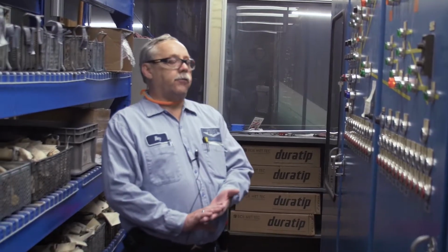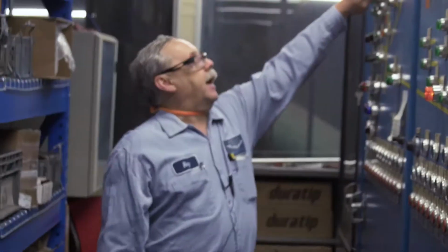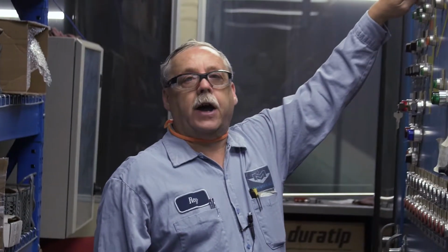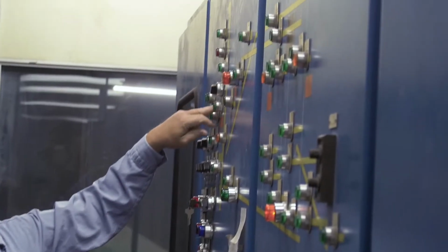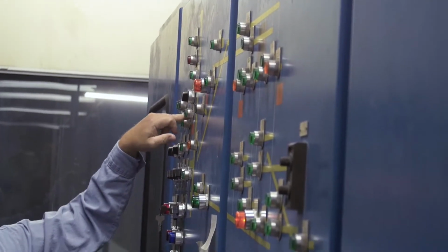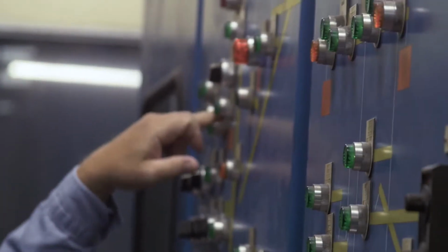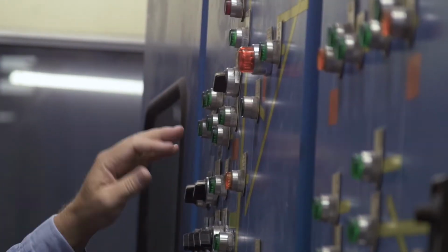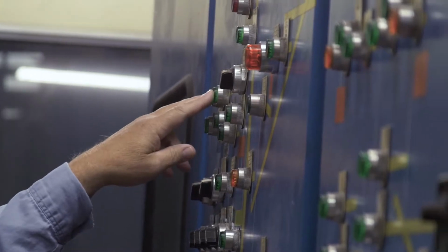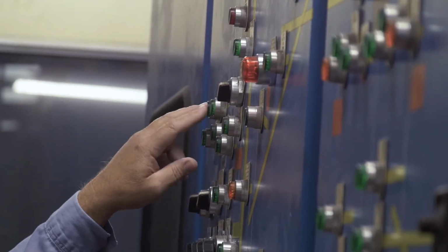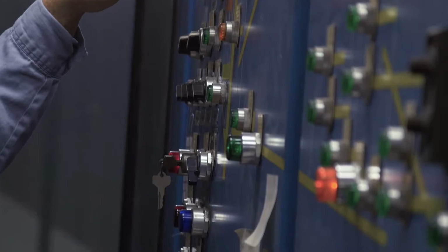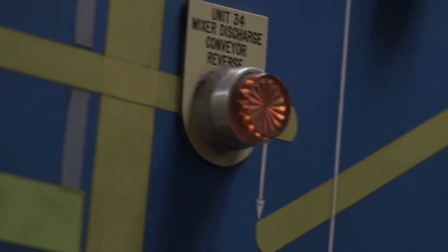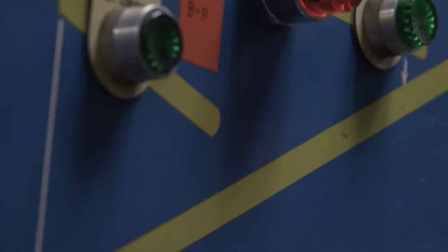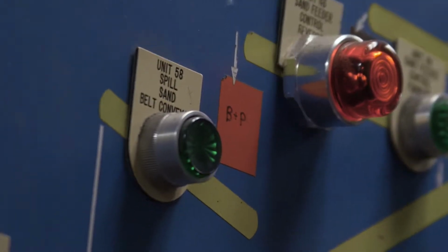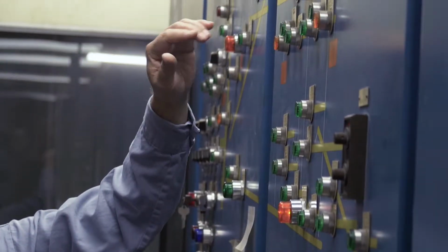Okay, this is a little description of our sand system here. We have a sand silo that contains about 105 ton of sand. Our mixer mixes sand at the rate of about 67 ton an hour. It's about 4,500 pounds of sand every 2 minutes and 10 seconds. And here's our additives. New sand and clay will get added into the 4,500 pound batch. We pre-weigh that before it goes into the mixer. It drops into the mixer, does the mixing, and goes out to the machine and gets distributed to the molding line, as it's called for automatic demand.